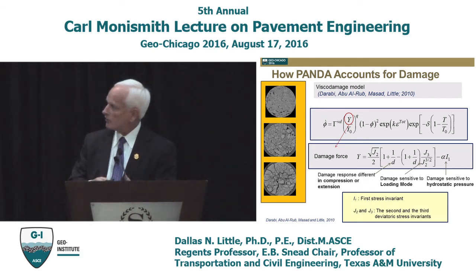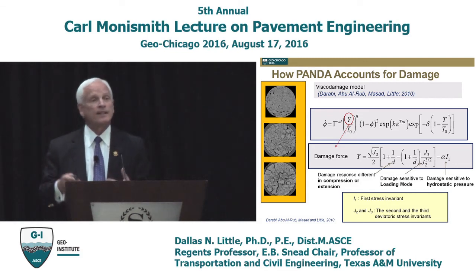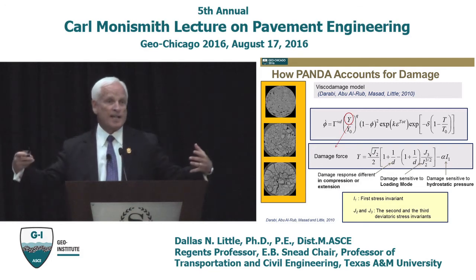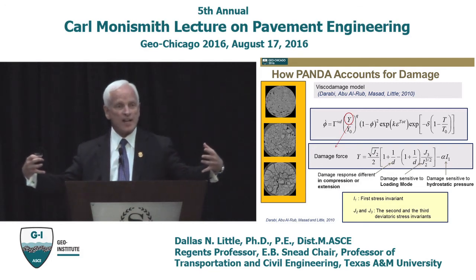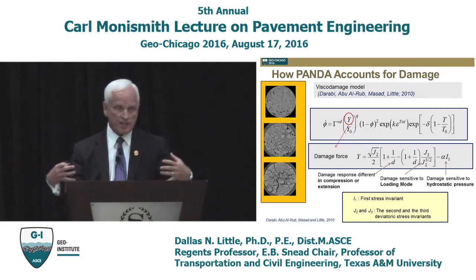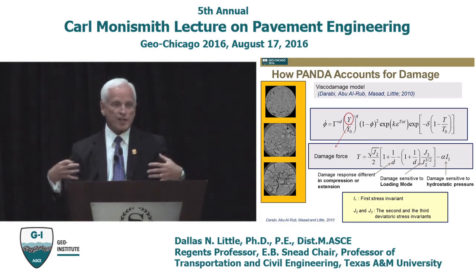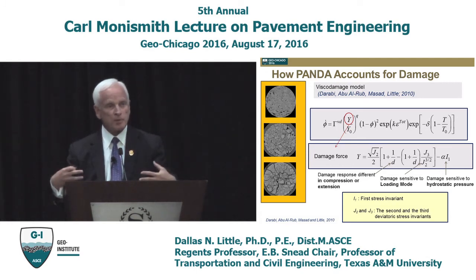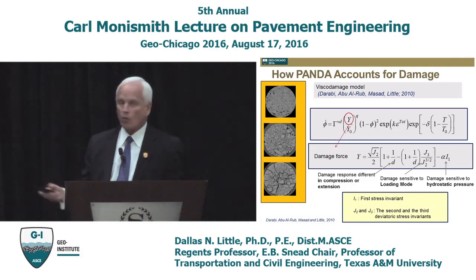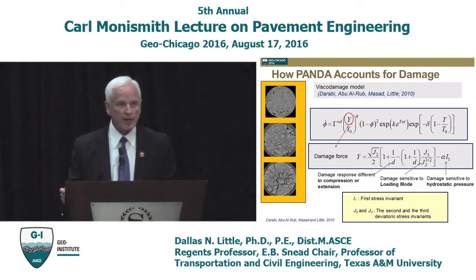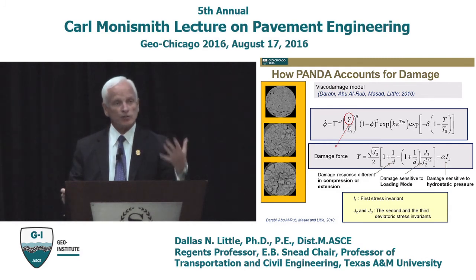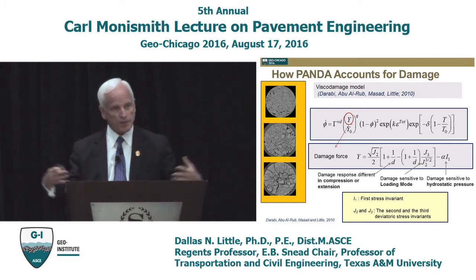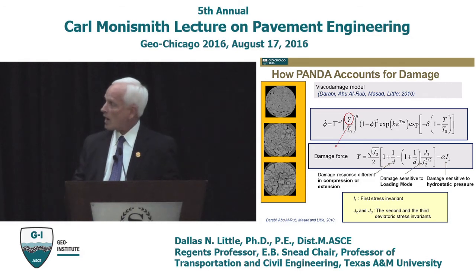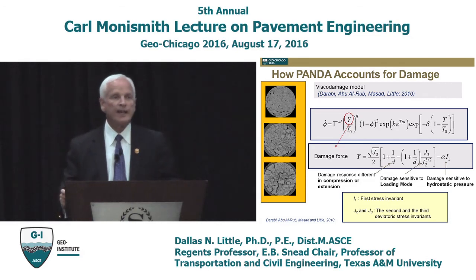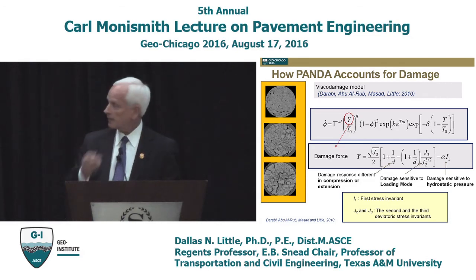So it accommodates a number of stress states to define whether or not a yield function or a damage force will be activated. And basically speaking, if the confinement stresses are such that they keep the yield stress or the shear stress intact, or they prevent it from developing, then the Y force will be very small. The driving force for damage will be very small. If, on the other hand, the deviatoric stresses overcome the confining pressures to a large degree, the Y parameter becomes large and the damage force becomes great.